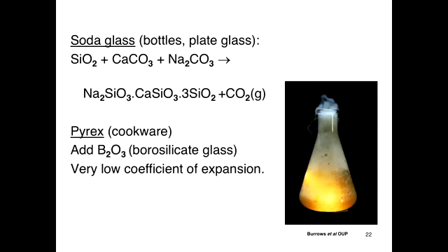It's got a high coefficient of thermal expansion, which means if I heat it up, the glass expands. Now if I don't do that evenly, then some part of the glass vessel will expand much quicker than other parts, and that will lead to the glass breaking. If we add B2O3, borates, to it, that has the effect of lowering the coefficient of thermal expansion, and we can heat up the glass and we don't get cracking occurring. So glassware is safe to use in the laboratory.